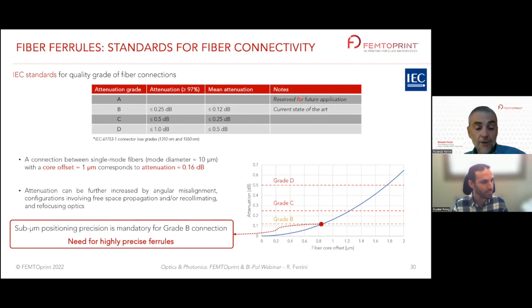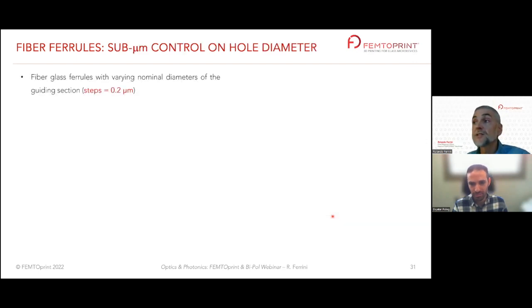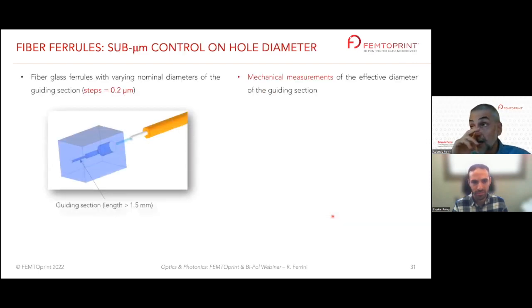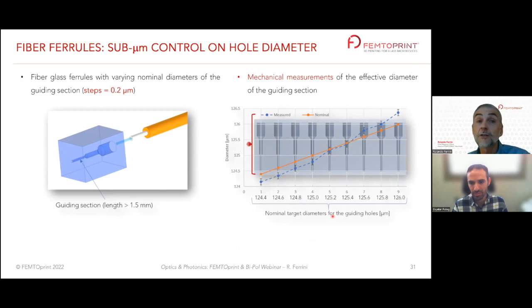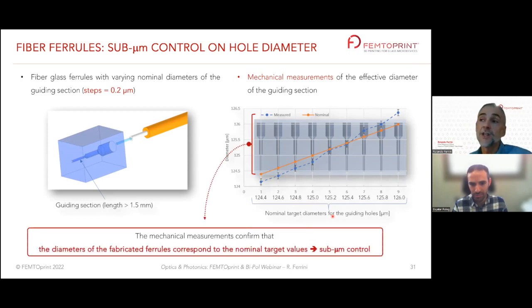And then you want to have smaller chips. This is because you want to have faster chips, and also you want to reduce the energy consumption, which means that at the end you end up with a single mode fiber with a mode a few microns in diameter in front of a chip with pixels of a few microns. If you have already 1 micron misalignment, you are off specs with respect to the standards for telecom in terms of losses. That's why customers want this type of precision that they cannot find with other technologies. And I'm talking here not about V-grooves, but 2D fiber arrays.